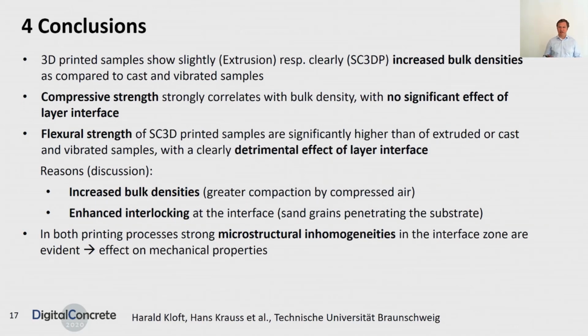As we could show, we have increased bulk densities in both cases, in case of extrusion and in case of shotcrete 3D printing, as compared to cast and vibrated samples. However, shotcrete 3D printing leads to the highest bulk densities. And this, again, leads to the highest compressive strength, which strongly correlates with bulk density. But here we could see no significant effect of layer interface or delay times. We could see such a clear effect of layer interface and delay times in case of flexural strength. And here the shotcrete 3D printed samples showed the highest and best performance as compared to extruded or cast and vibrated samples.